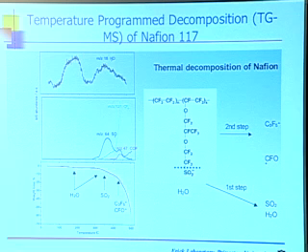So if we set our mass spec to mass 18 while we carry out this temperature transition, we observe two fairly ill-defined peaks right there. One of them starts at about 100 degrees and continues above that temperature. Now, we dehydrate to some extent, but not really well, the Nafion before we put it into the TG mass spec. Nafion just sitting out in the air will rehydrate. It's a strong acid. It's rather hydrophilic, so water will be sucked into it. And so what this is, obviously mass 18 is water, is there is a certain amount of water that we have just left in our membrane. You get up to 100 degrees, and it boils out.